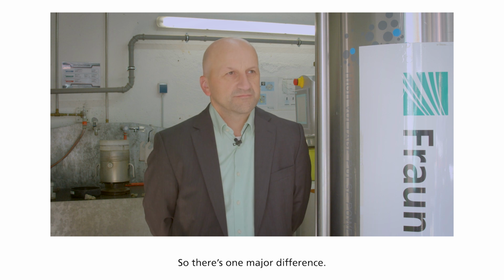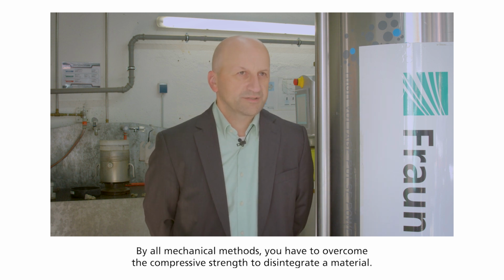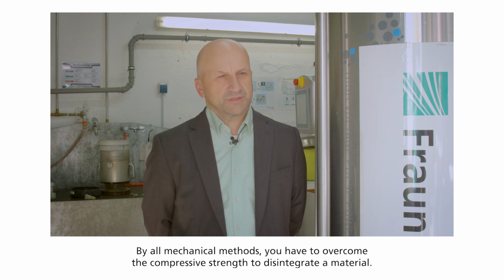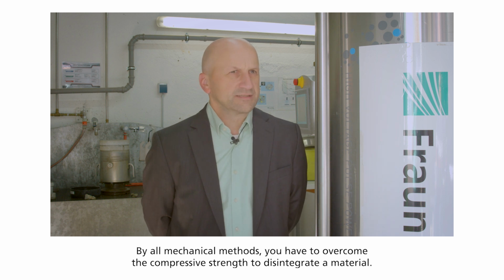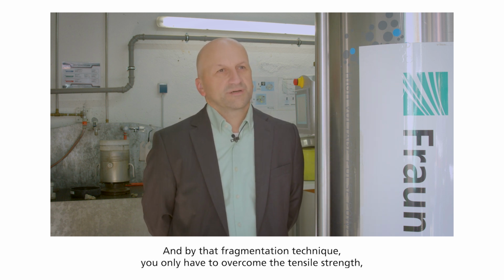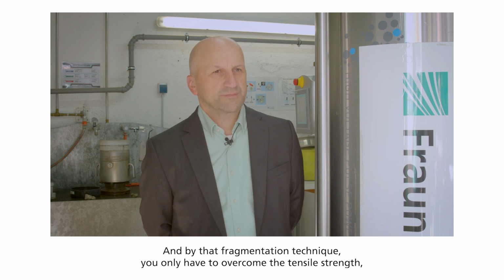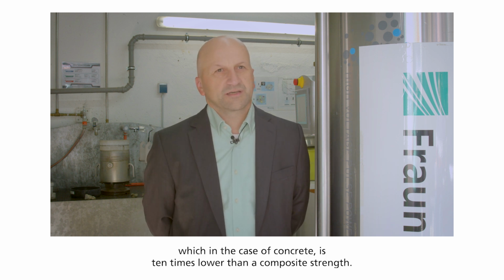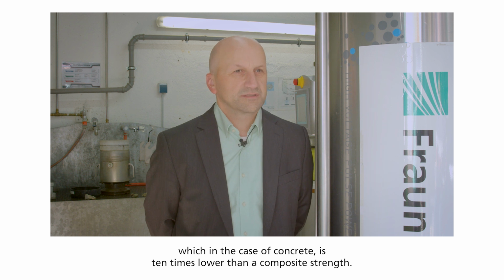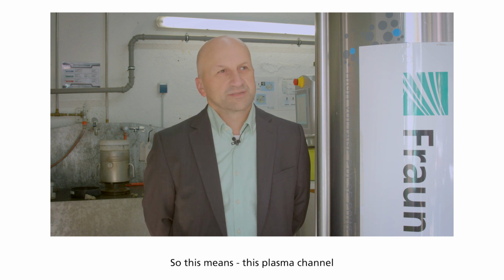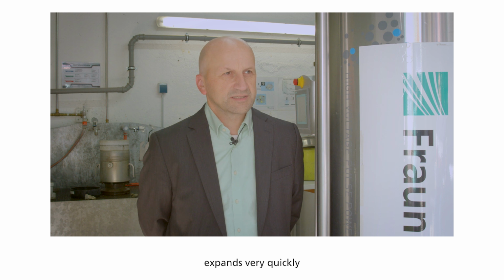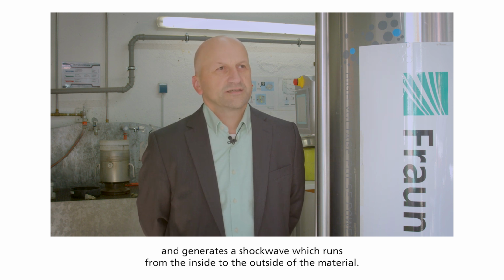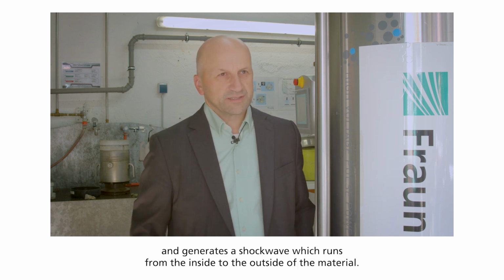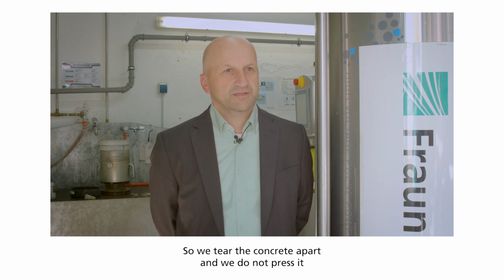So there's one major difference. By all mechanical methods, you have to overcome the compressive strength to disintegrate a material, and by the fragmentation technique you only have to overcome the tensile strength, which in the case of concrete is 10 times lower than the compressive strength. So this means this plasma channel expands very quickly and generates a shock wave which runs from the inner side to the outside of the material. So we tear the concrete apart and we do not press it until